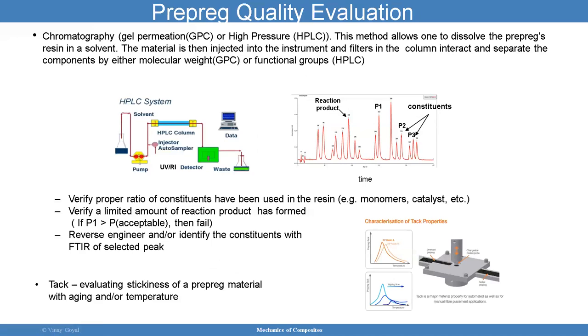The prepreg quality evaluation, again, we talked about GPC, gel permeation chromatography, or high pressure chromatography. And so these methods usually allow one to dissolve the prepreg resin in a solvent. We take the material then and inject it into the instrument, and then we filter out the different components by either molecular weight or functional group. So here you can see an example of that.